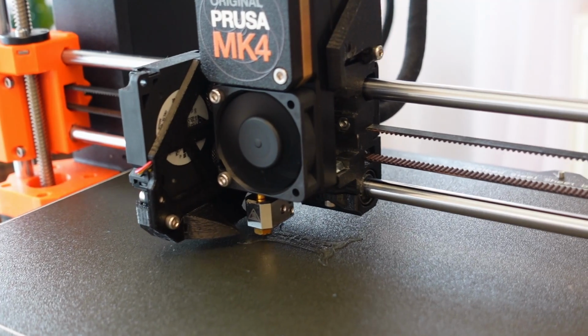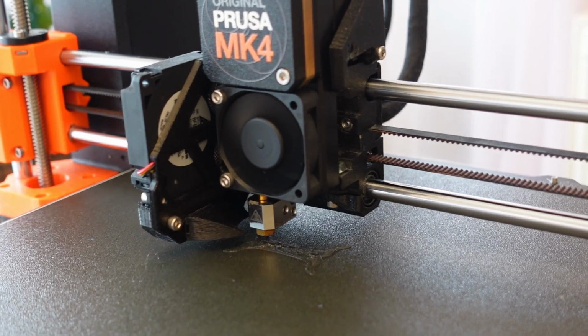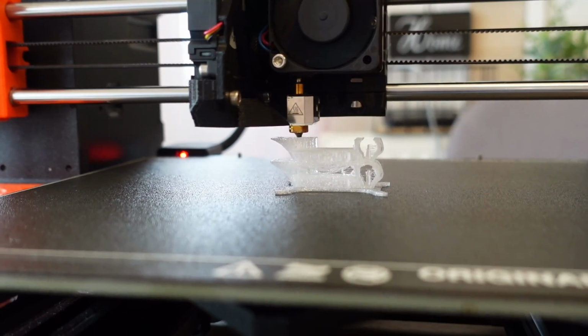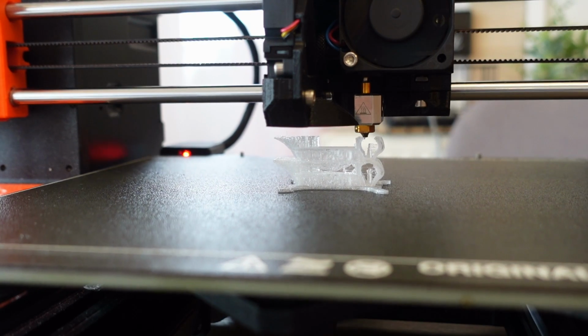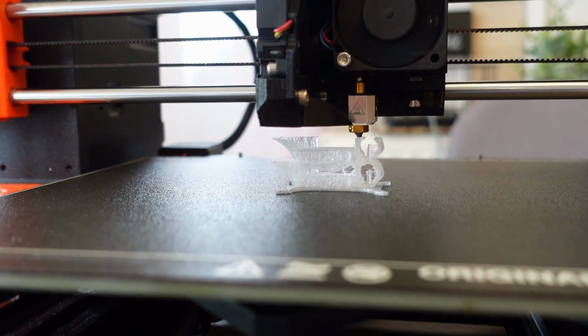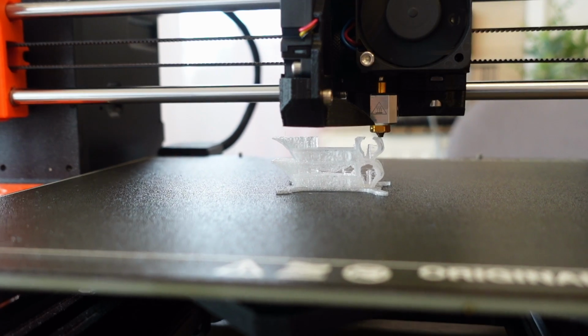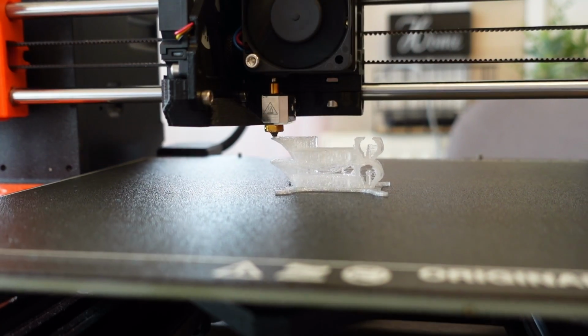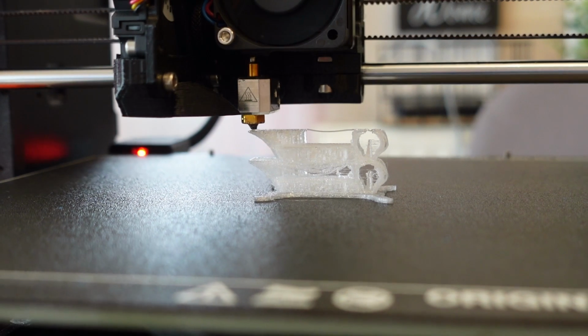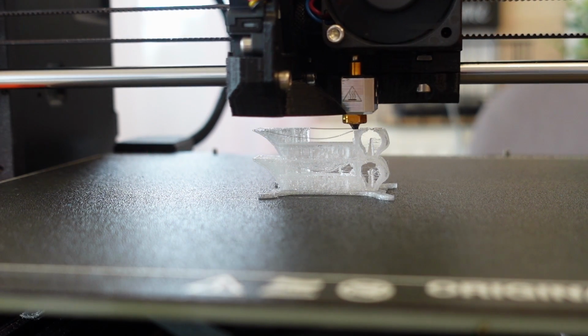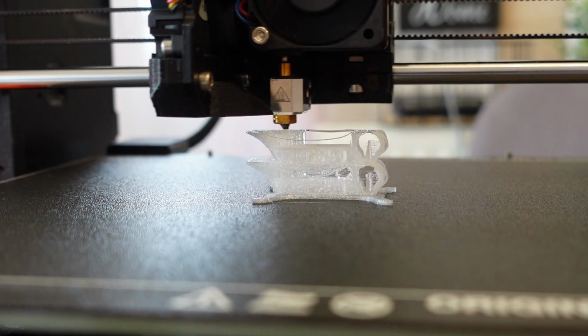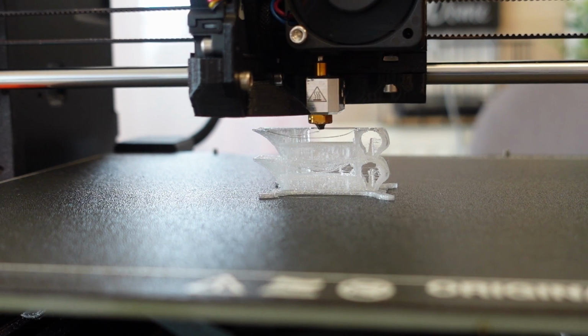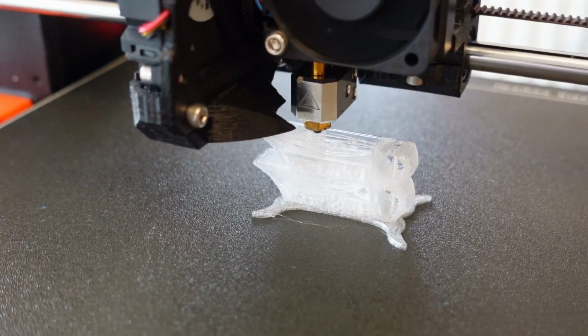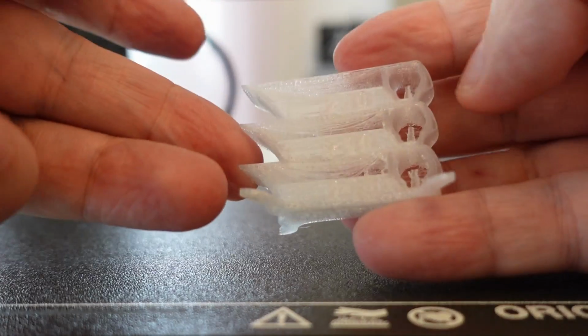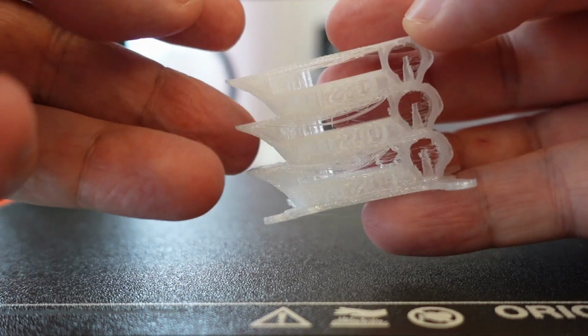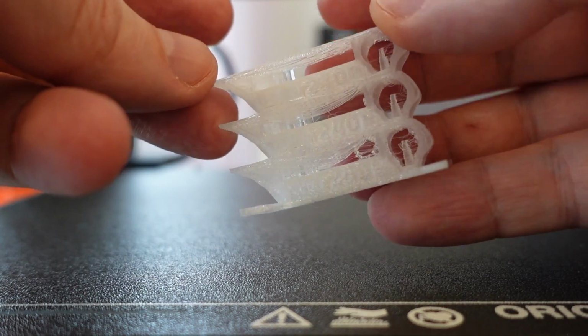It's a little bit hard to see because this is transparent color, but the first layer is okay. I want to show you this. So all this mess you can see on the first element is basically because of the failed bridging, but actually there is no stringing, and this you can see on this second element. And this is that bridging moment. And again, when it is a long bridging on this side, it fails. And interesting to see that even the bridging was successful on the last element, but